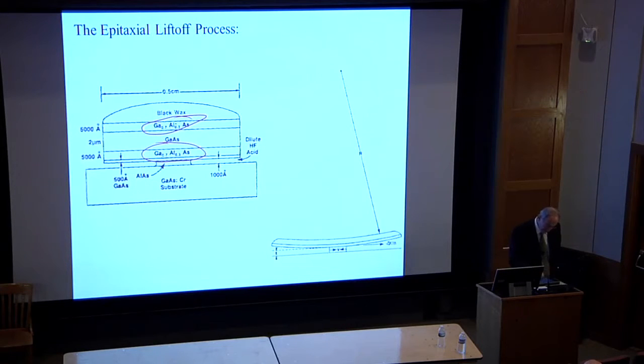Now, one of the things about this, of course, they gave a Nobel Prize for the double heterostructure to Herb Kroemer about 15 years ago. But one of the things you know is that once you get the idea that you can use aluminum arsenide, so let's grow a very thin layer. Before we grow anything else of the active electronic device, let's grow a thin layer of aluminum arsenide just to get started. We're allowed to do that. It is the same lattice constant as the gallium arsenide substrate. Now, they're very similar materials, and so they work together very well.